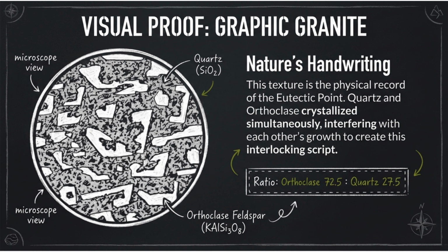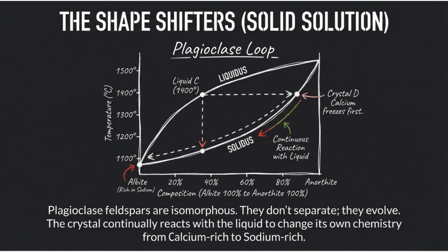In typical graphic granite, the composition might be about 72.5% orthoclase and 27.5% quartz, a ratio that reflects their eutectic proportions. The end result is a rock where the texture itself becomes evidence, almost a signature, of the thermodynamic conditions under which it formed. Plagioclase feldspars are remarkable because they form a continuous solid solution between two end members, calcium-rich anorthite and sodium-rich albite. Instead of separating into distinct minerals, plagioclase crystals can gradually change their internal chemistry as conditions evolve. At high temperatures, calcium-rich compositions crystallize first.